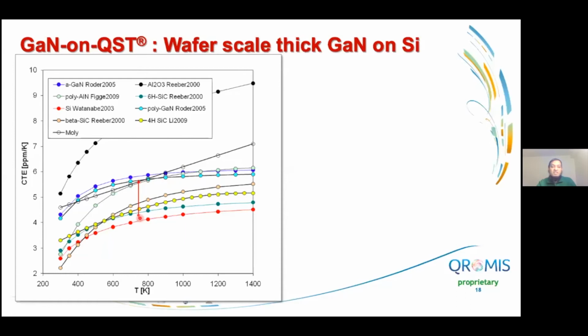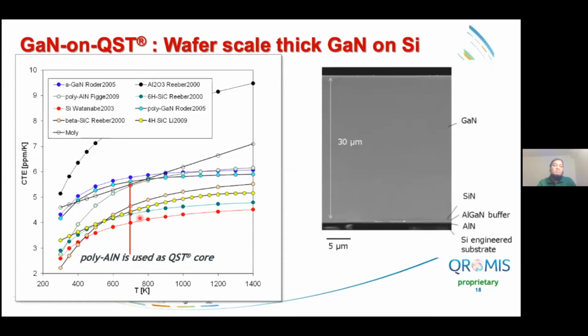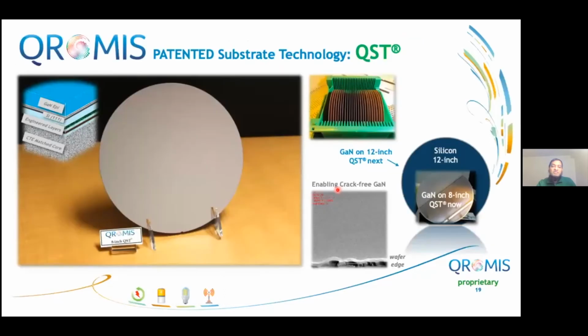But these substrates from our collaborators use aluminum nitride as the core, and the CTE mismatch between the polycrystalline aluminum nitride and GaN is minimal, which helps us develop very thick epi without cracking or high defect density. Here is an example of a 30 micron thick gallium nitride grown on this QST technology. And better news is these wafers can be grown at 8 to 12-inch wafer scale. That gives us an immediate opportunity to scale up our device technologies and fabricate in a commercial fab.